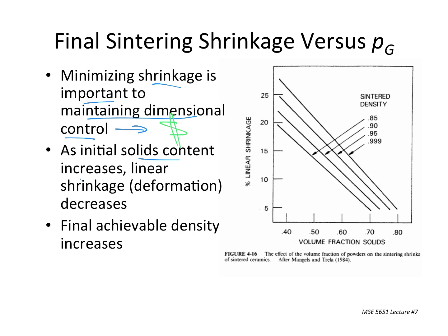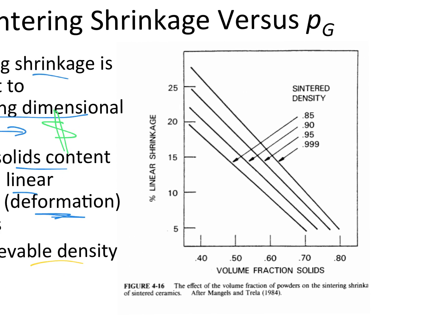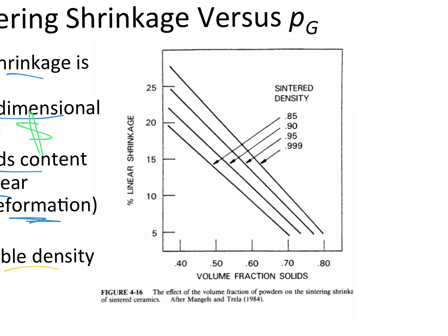As the initial solids content increases, linear shrinkage, or the potential for deformation, decreases. That should make sense. And then ultimately the final achievable density will also increase. This is showing you a really interesting plot, which is related to that previous equation, in which we start with different volume fractions of solids, 40, 50, 60, 70, and 80% solids, and we look at the percent linear shrinkage necessary to get to specific final sinter densities.